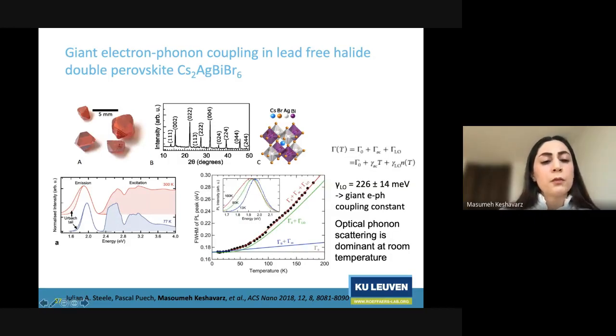So if we measure their photoluminescence at different temperatures ranging from 4.2 Kelvin to 300 Kelvin, which is room temperature, and we fit each of these curves with a Gaussian, we can extract information such as the PL peak center or full width at half maximum of the Gaussians. By analysis of the full width at half maximum of the Gaussians as a function of temperature and using this model, one can access the electron-phonon coupling constants.